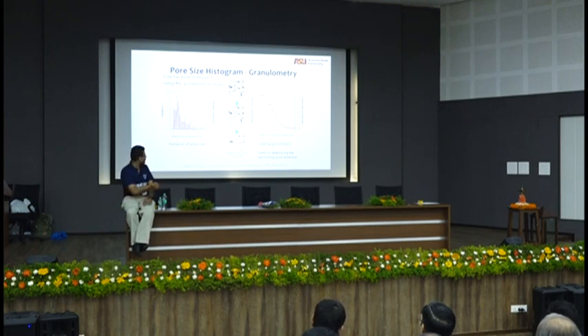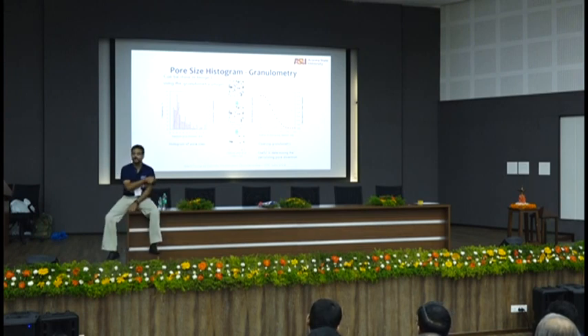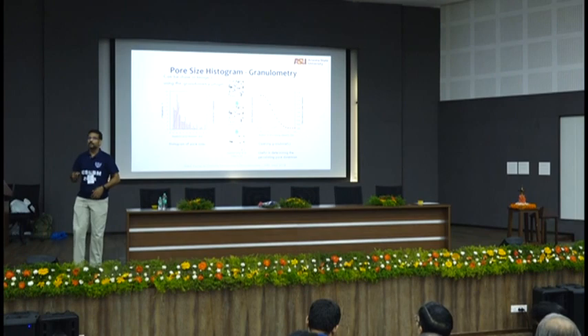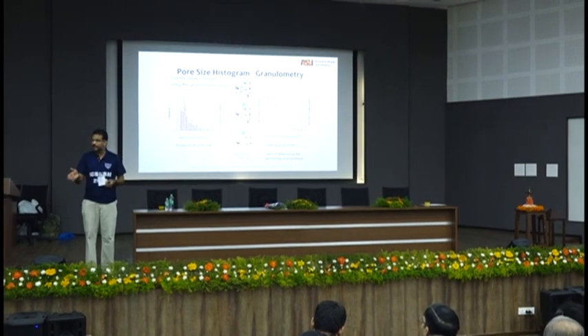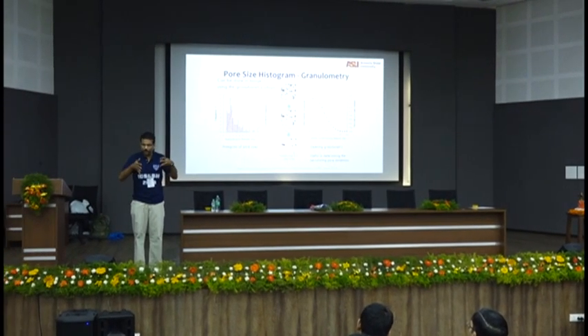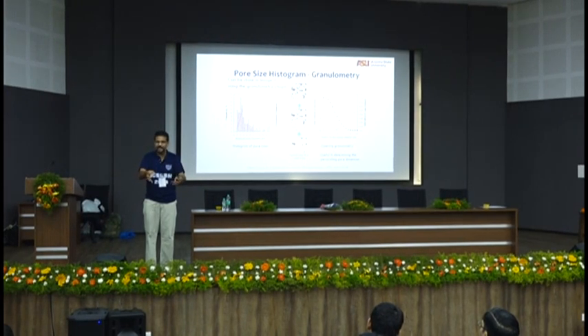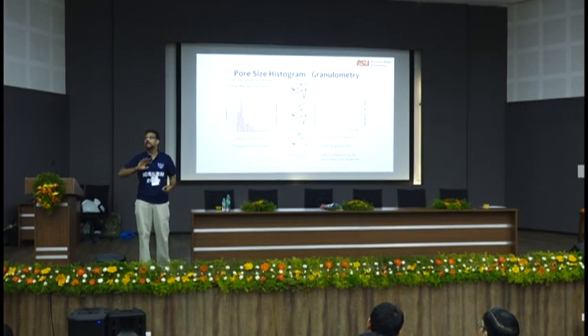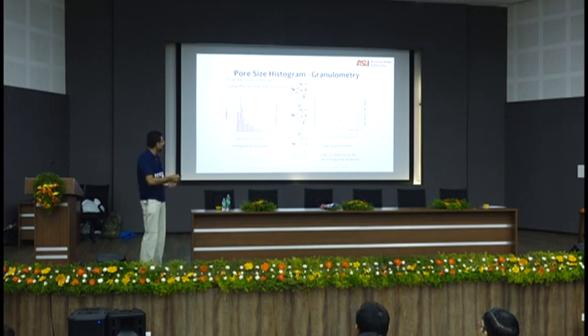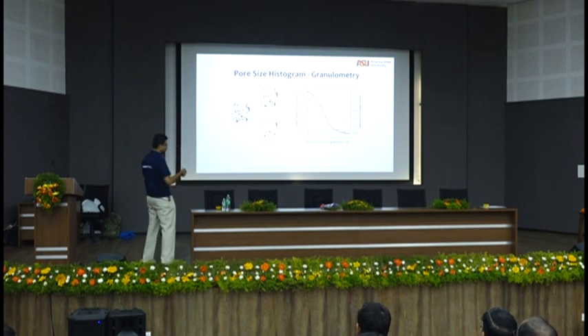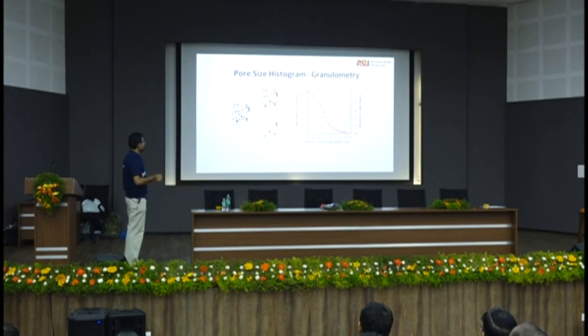Okay, that's one way of doing it. So it's useful in determining the percolating pore dimension. Percolating pore dimension is the most important pore dimension because percolation means transport, right? If it starts to percolate, if you get to that percolating size, that is a size beyond which you will have transfer through those pores very fast. So you know what that size is, and your aim should be to make sure that you have the right percolating size. Okay, same idea again, another picture from another set of images. So you get another percolating radius.